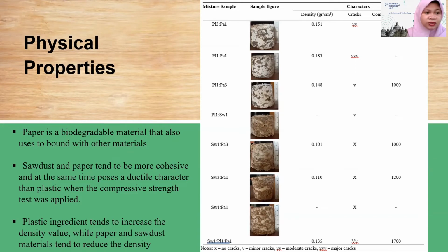Some features used to identify the physical properties include the density, the presence of cracks, and compressive strength. The greater the ratio composition of sawdust or paper in the mixture ingredient, the higher the compressive strength will be. The ductility also suggests that the materials are more flexible and not that fragile. The plastic ingredient tends to increase the density value, while paper and sawdust tend to reduce the density.